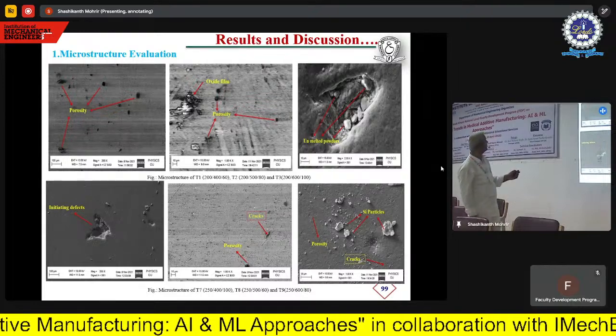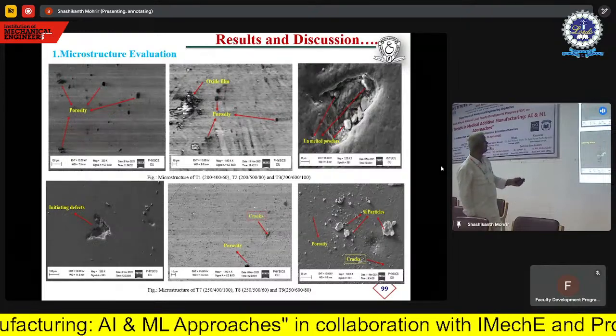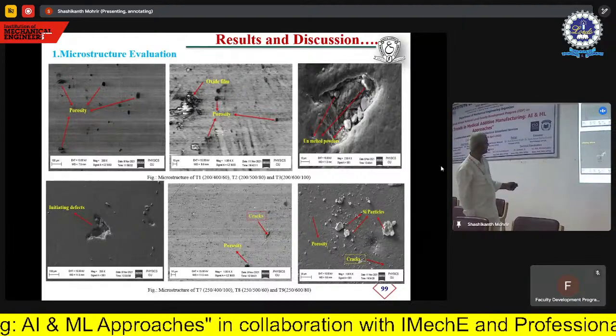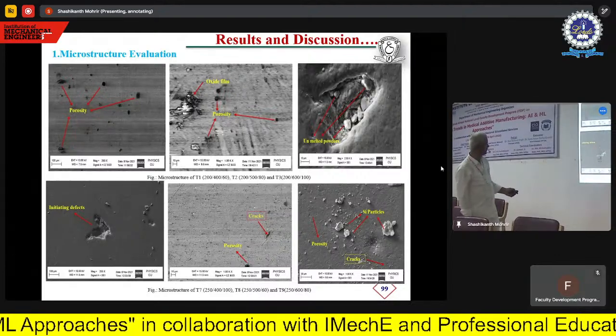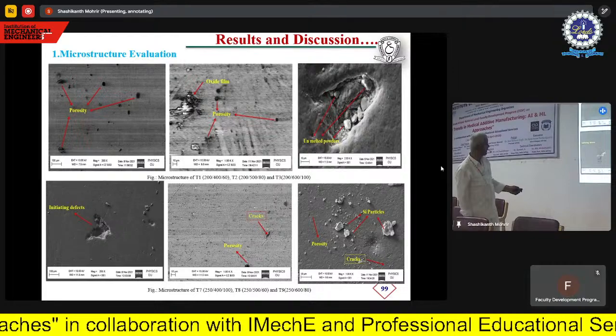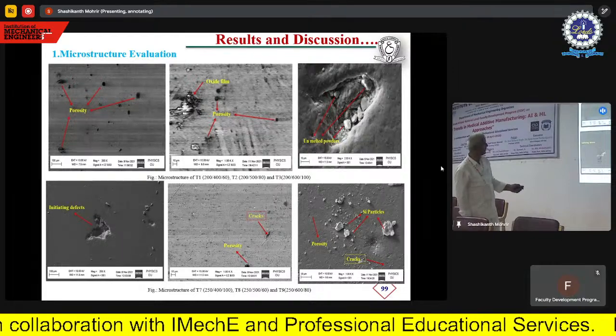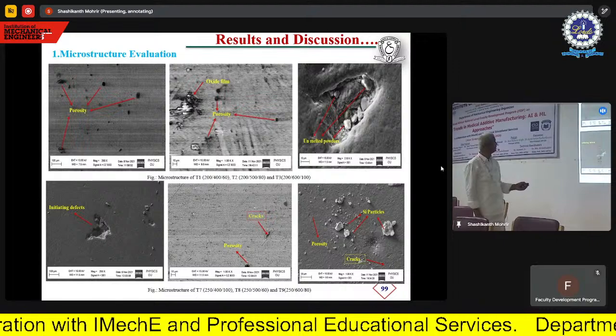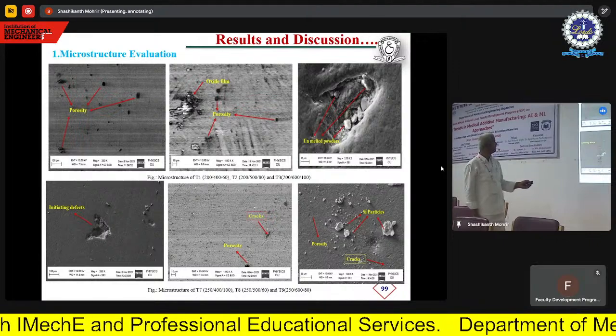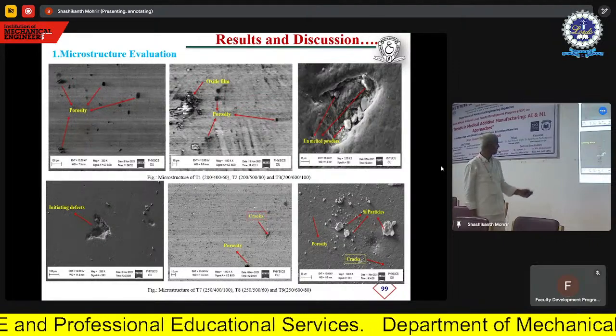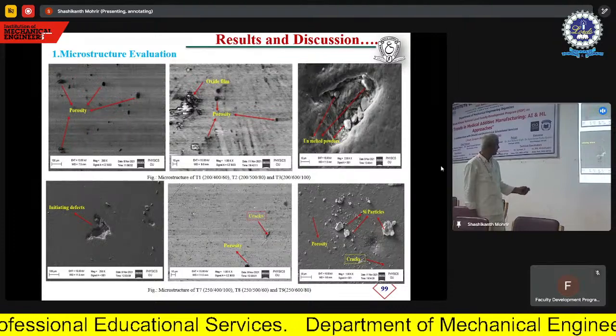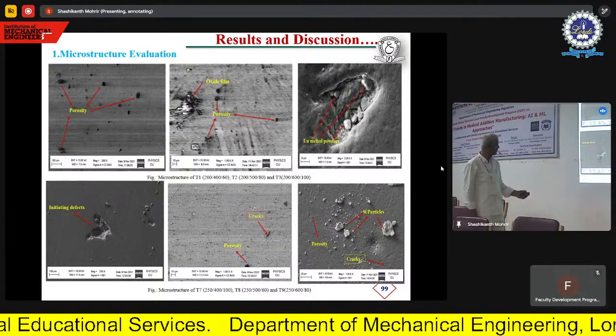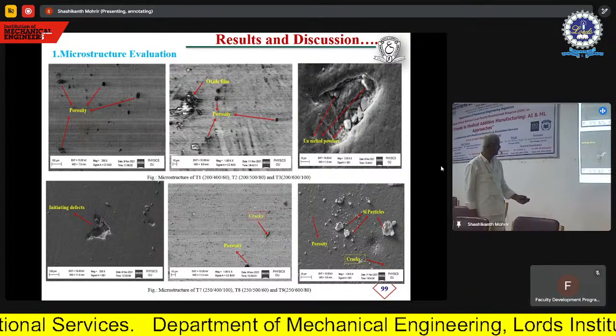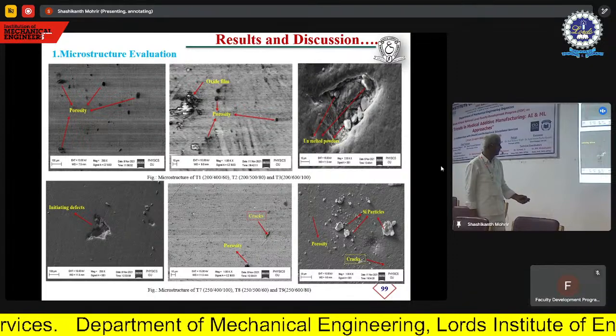Defect-free component. You see porosity, oxide formation, unmelted powders, initiating defects, here porosity, cracks. So we have to avoid this. So this is for T1, T2, T3. Here this is T7, this is T8, and this T9. And these are the process parameters.